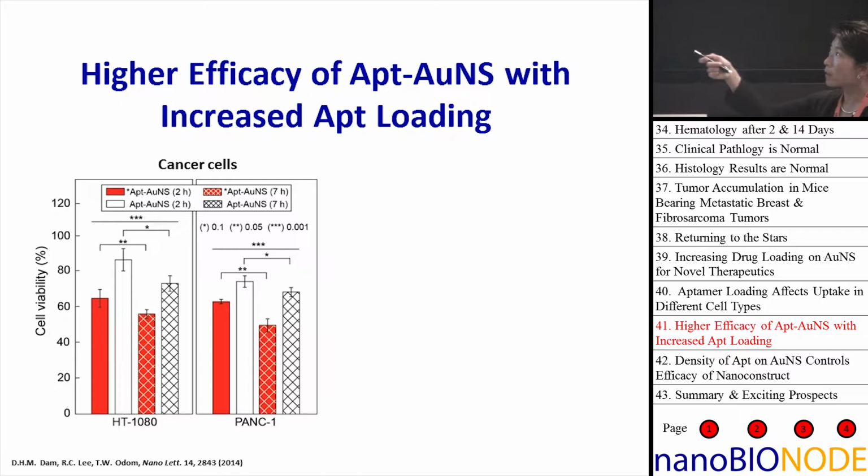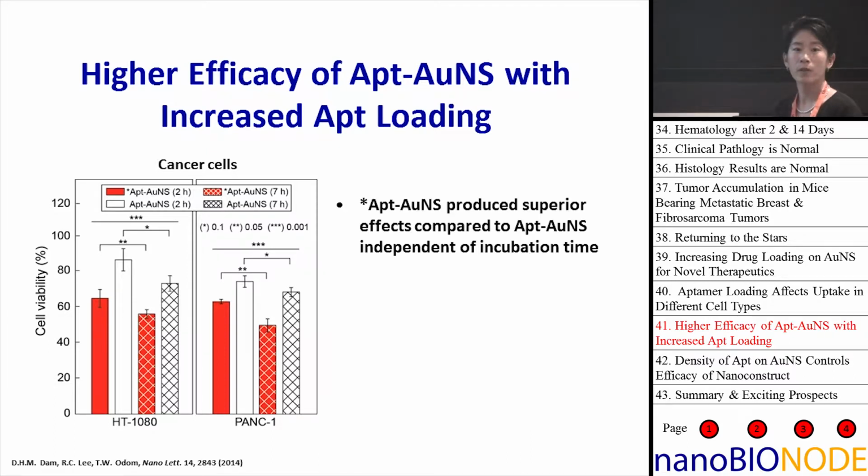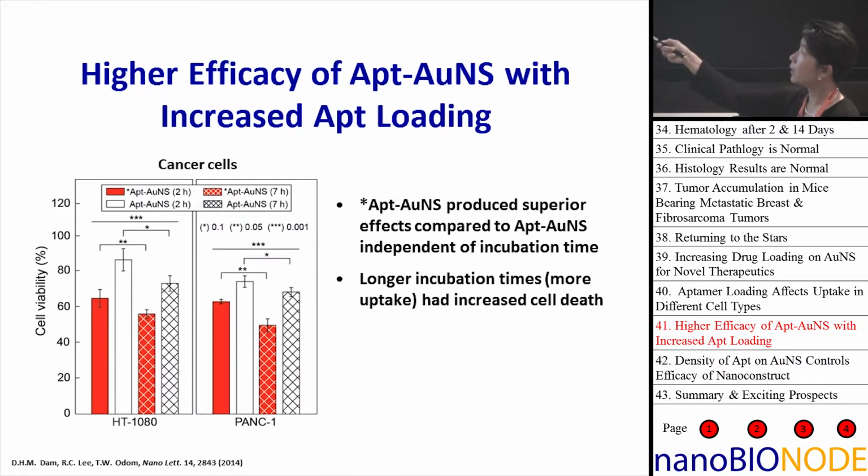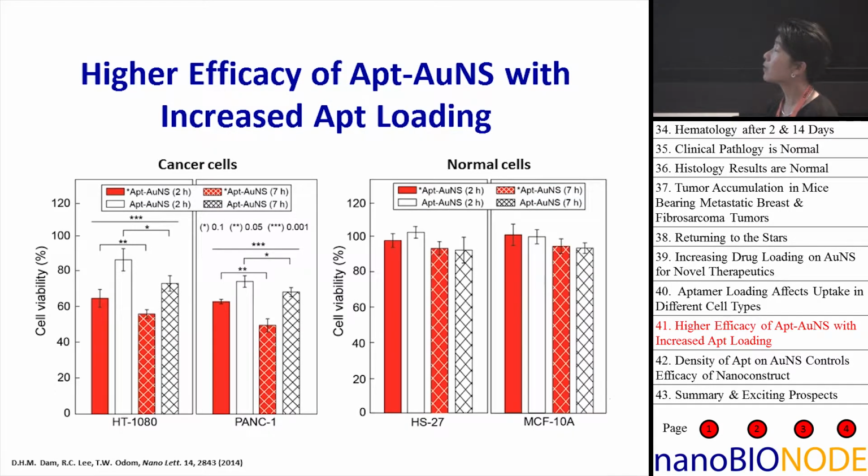So the most important thing that we found out is that you got higher efficacy with increased loading. So that was sort of surprising. What that means is that not only do you have this highly densely loaded drug on the particle, but they're somehow interacting in a multivalent way, which is also a synthetic procedure. It's called multivalent effectors, where you design synthetic ligands that can bring multiple cell surface receptors together. But in this case, we're exploiting that type of way to get greater efficacy. And so you get superior effects with high loading compared to not. And as you might expect, longer incubation times had more cell death.